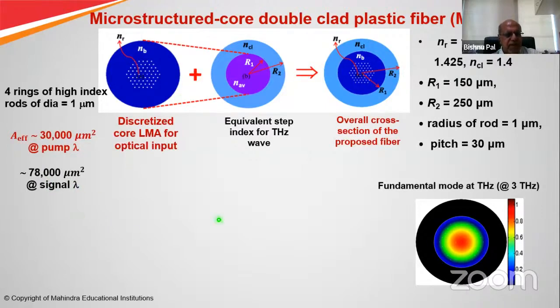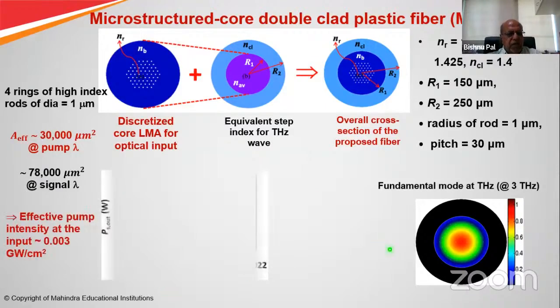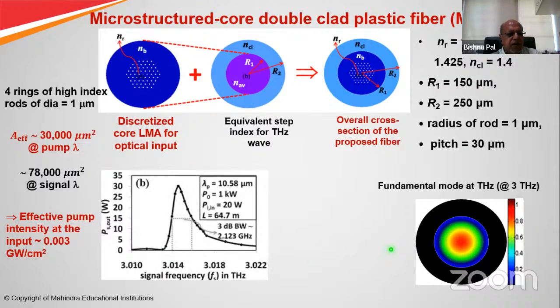So the signal is at a terahertz frequency. Because of this very large effective mode area, even though I have pumped in a very large power, the overall power per unit area is relatively small. So the effective pump intensity is rather small. It is only 0.003 gigawatt per centimeter square.